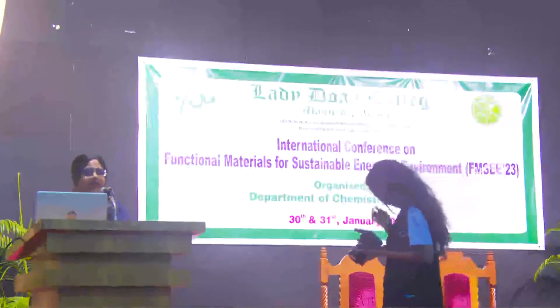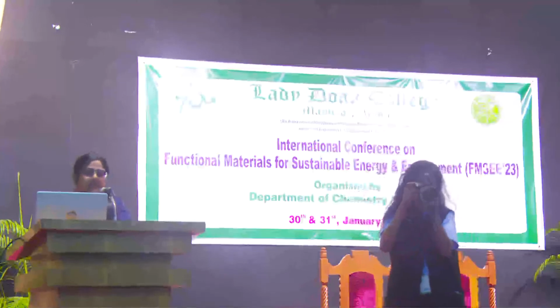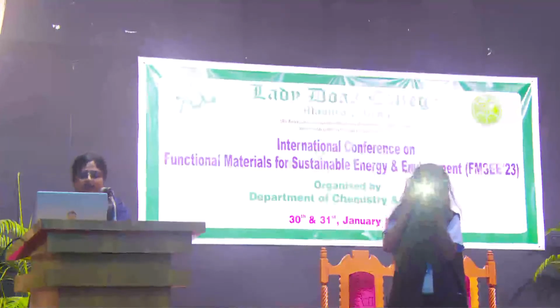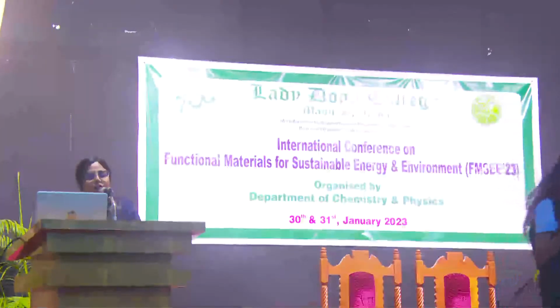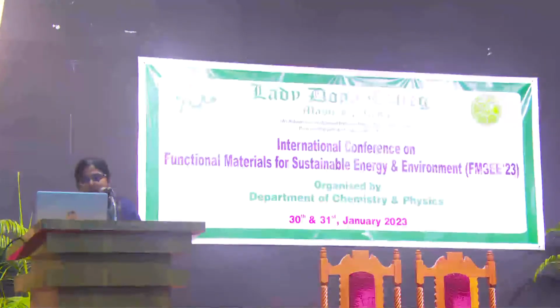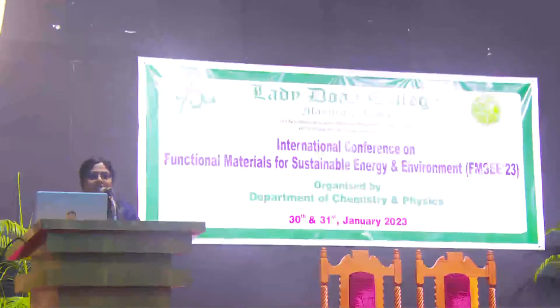After we characterized these 3 samples, from the FTIR studies we found that there were strong carboxylic and hydroxyl groups present, which paves the way for the pseudocapacitive behavior of the samples. There's also a nitrile group present, which indicates good conduction behavior. And when compared to the plain activated carbon, the doped carbon had some gradual differences, indicating the interaction of the metals with the carbon.